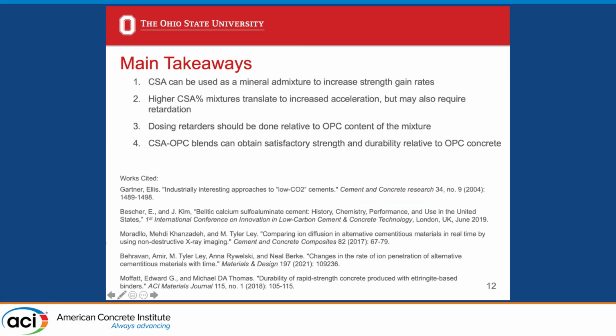Great, so the main takeaways from our study, we definitely can use CSA as an accelerating mineral admixture. It will accelerate both our setting times and our initial strength gain rates. Use of higher proportions of CSA will increase the rate of acceleration. But if we are not careful, we may then need to go back and add in an additional retarder to control that setting time. Dosing of the retarders is most consistently done based on the amount of OPC present in the mixture rather than total cementitious content or CSA content. And finally, we found that CSA OPC blends obtain satisfactory strength and durability relative to OPC, and maybe in some cases improved performance.